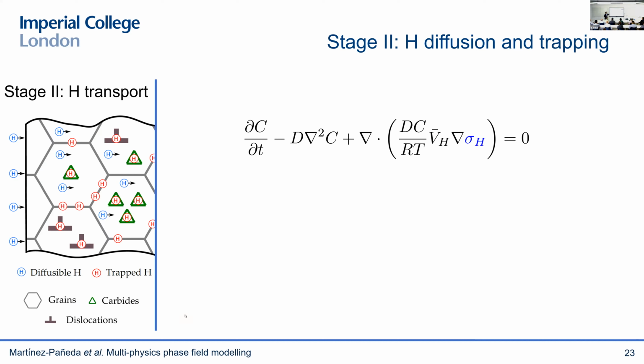And the easiest way to do this is by using this kind of extended version of Fick's law, where you have hydrogen driven by gradients of concentration and also by gradients of hydrostatic stress. So this coupling with the mechanics is quite important. Hydrogen will accumulate in these areas of high hydrostatic stress. In fact, if you get the steady state solution of this problem, you will see that you end up with this exponential term here. So you have this hydrostatic stress inside of an exponential term. So you get a lot of hydrogen accumulated near stress concentrators such as cracks.